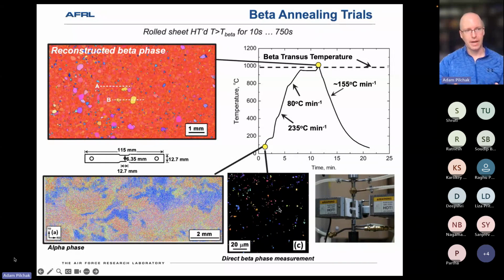The classical theory, things that have been measured by, say, synchrotron or neutron diffraction heating experiments, would say that as the alpha phase dissolves, the beta phase that's already present tends to grow in size. So you don't formally recrystallize and get new beta orientations upon heating. So what that would suggest is if, in your mind, you expand these colors out, so all the black is alpha, right? So that's dissolving. And as you expand these different colors out that represent the beta orientations, eventually you would get contact between, say, blues and reds, pinks and greens, yellows and purples. And so you would expect that when you get just above the beta transus, you would have this nominally random